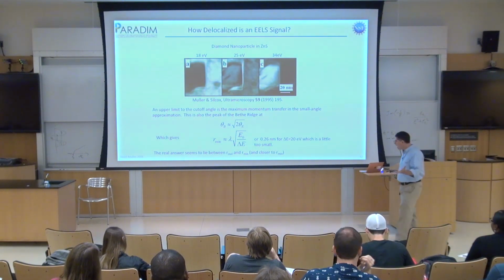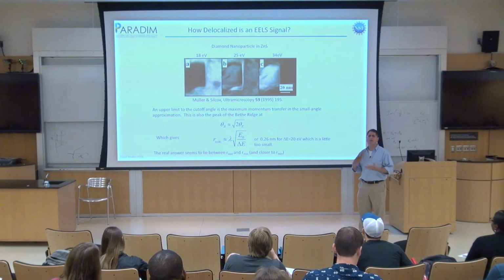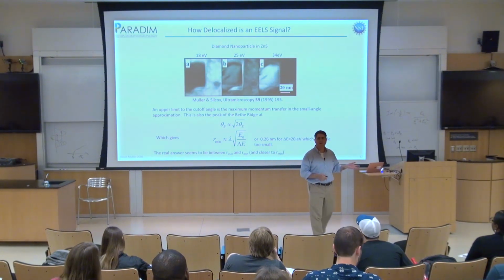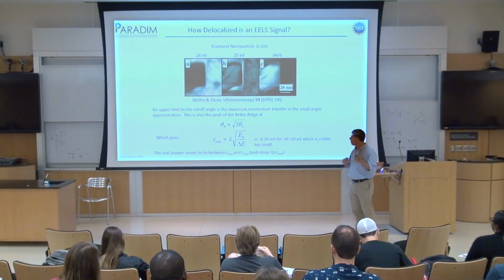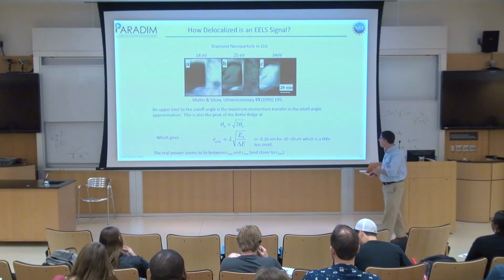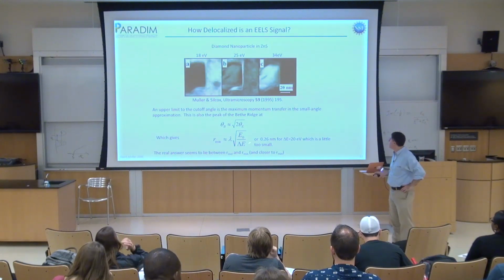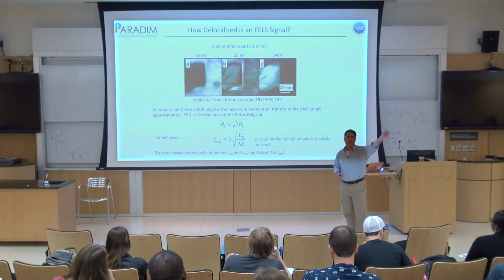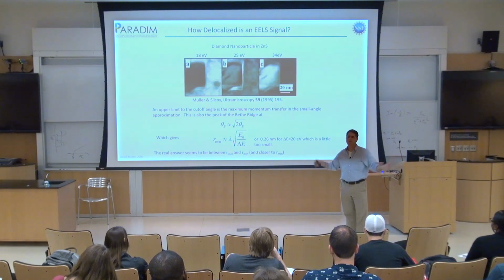So when we talk about blurring and inelastic scattering, there's actually a couple of different length scales involved that makes this a little bit tricky. And it's a little dangerous. It's not that everything blurs out to a couple of nanometers because I'm at a low energy loss. No, it gets worse than that. You can calculate an analytic cutoff for what you'd expect your resolution to be. And what you'd find is that the full width half maximum is always very small. The 80% radius, which is the tails that Lena talked about, is big.